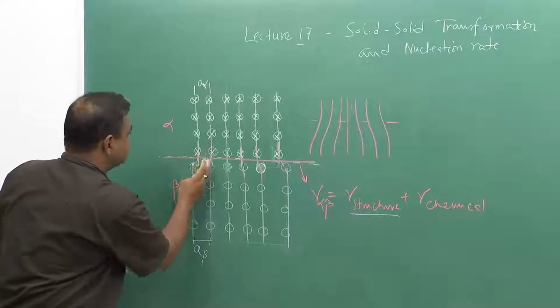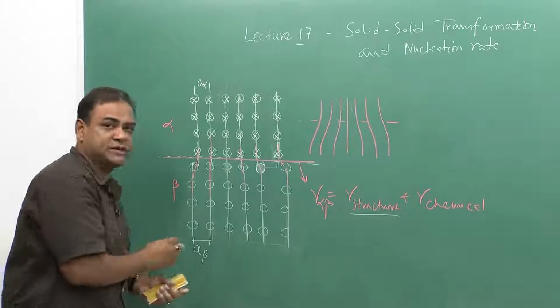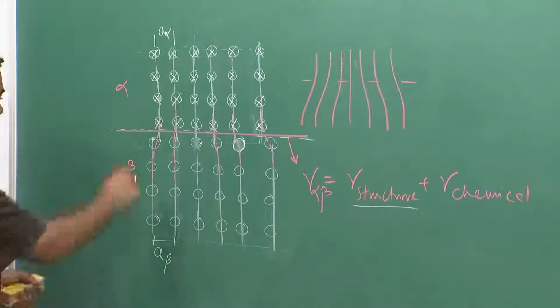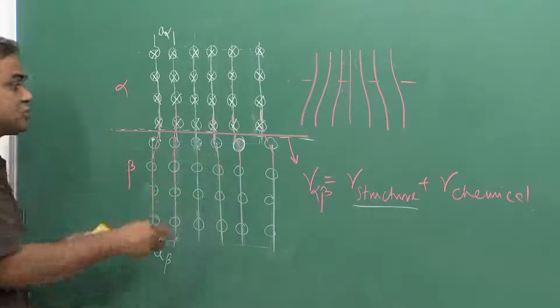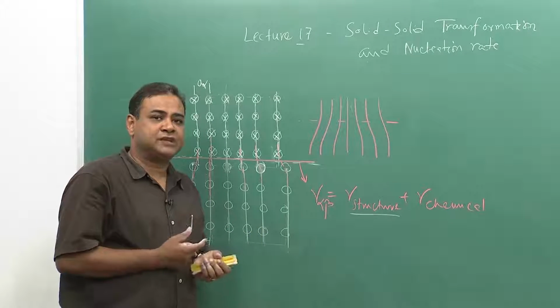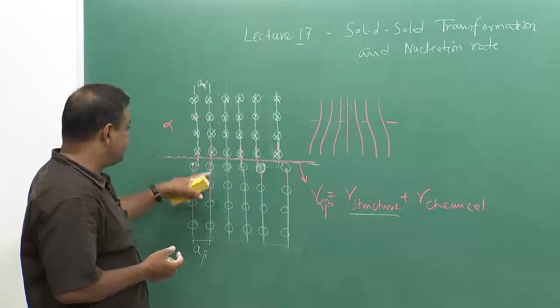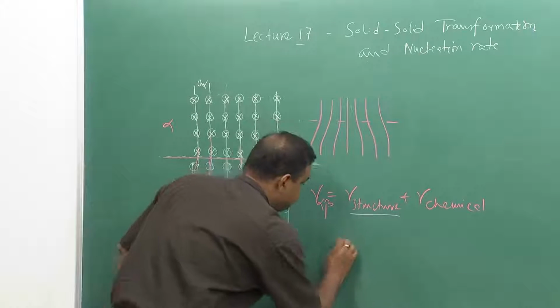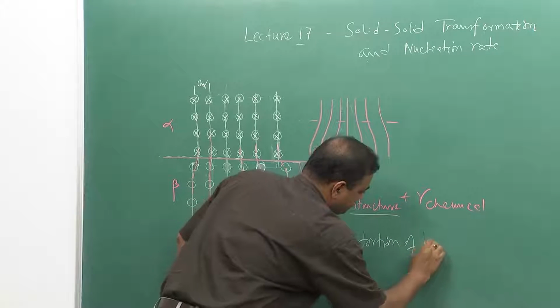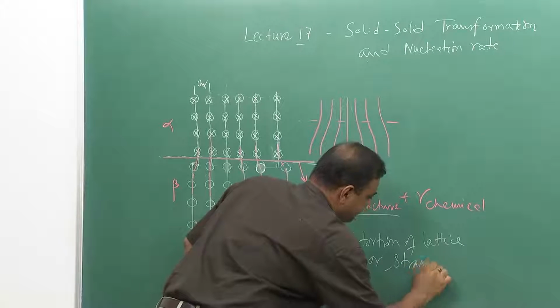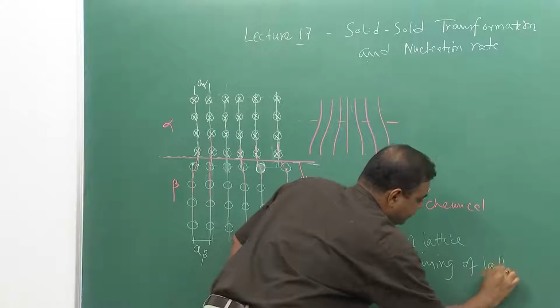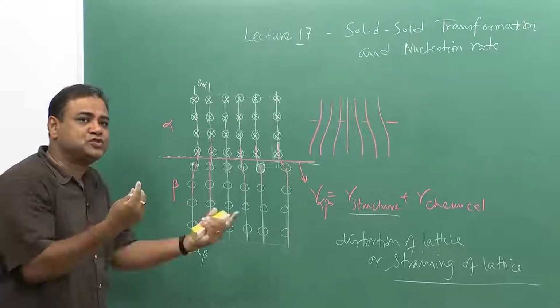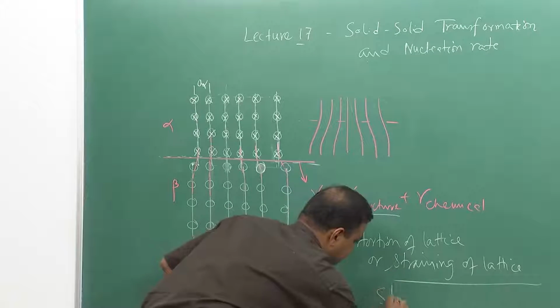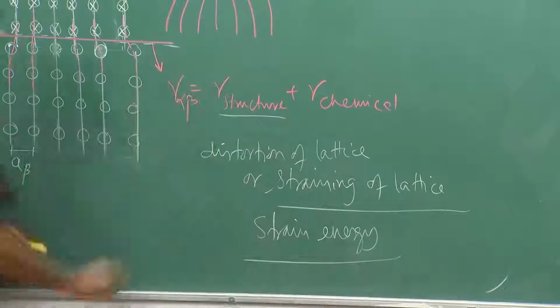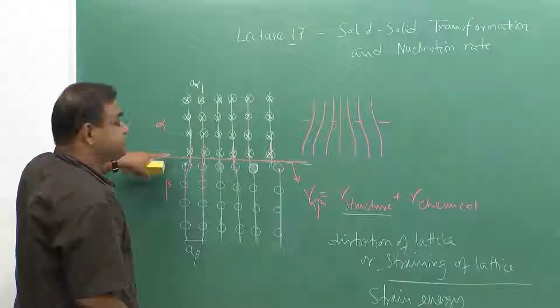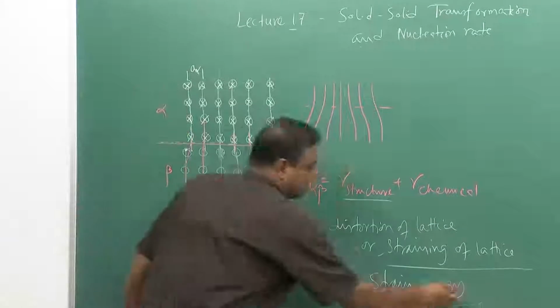You can see this, in order to have a match, these lattices are not flat, not straight, rather they are distorted, and this distortion is going inside the lattice. So, distortion has started from here, it has gone inside. This distortion is related to the structure effect. That means, because of the structural matching, they are having distortion, and this is called distortion or straining of lattice. And whenever there is a straining of lattice, it would also associate with some energy which is called strain energy. And this strain energy is not situated at the surface, rather it is going inside the volume. That is what this is, a volumetric energy.